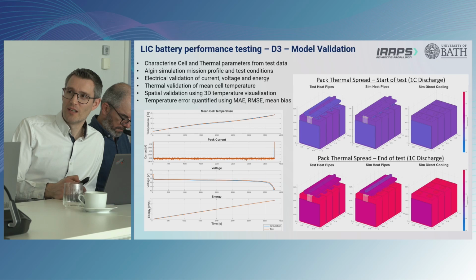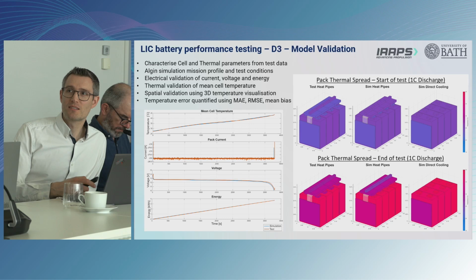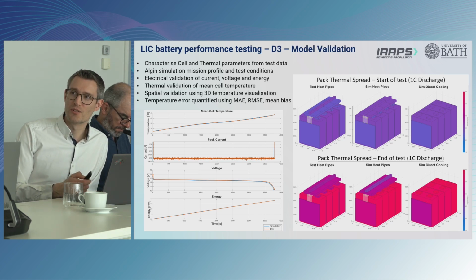I mentioned that we parameterized a digital twin. We took an approach to base this on a lumped parameter thermal network type approach. So it's a relatively simplified thermal management simulation, and we wanted to see how good a result we can get with a relatively simplistic model. It's much lighter and much faster to execute than a full finite element type model. But as you can see on the left-hand side, we actually get extremely good results. This is quite an interesting learning point, that we can get very good results with a quite lightweight model.